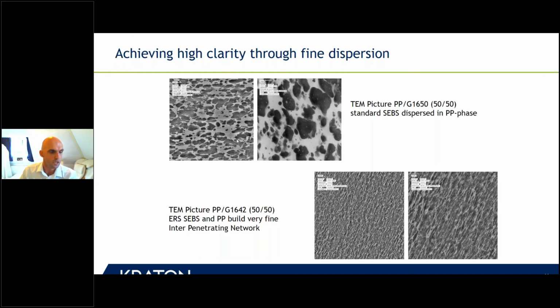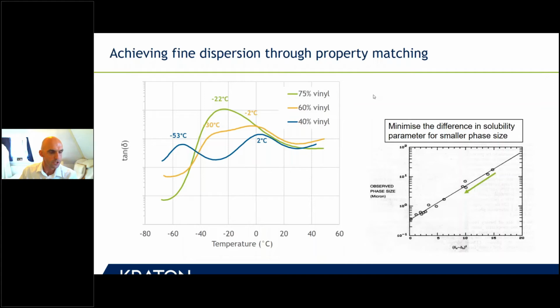If you have a difference in refractive index between materials that you blend, you get all kinds of scatter effects. But if the domains are very small, those scatter effects are less. So the good news is that you can make very nice transparent compounds here. Why is this working? Well, there's actually two reasons why this is working. It's a matter of property matching. And on the left, you see an image showing the thermal properties of the rubber block as measured by DMA.